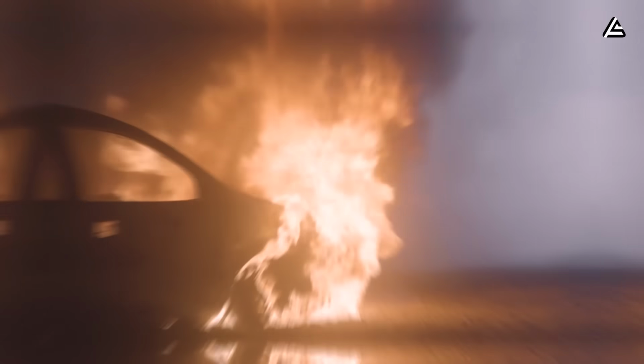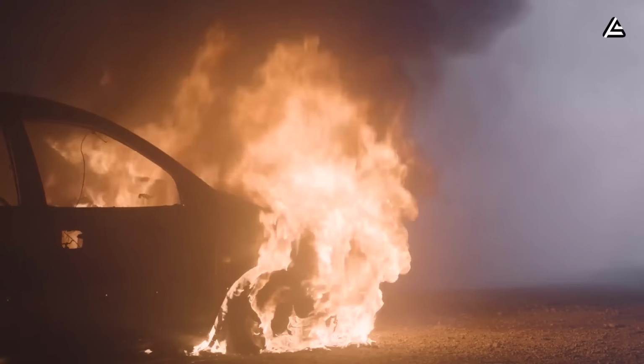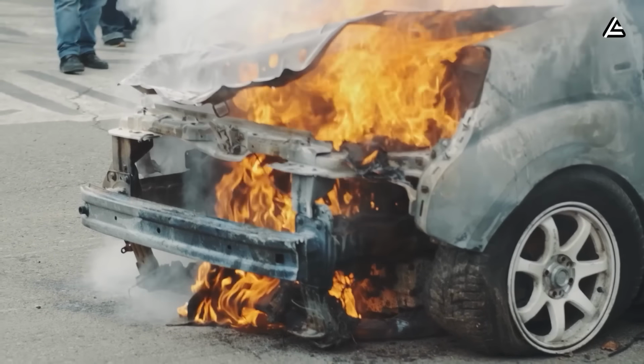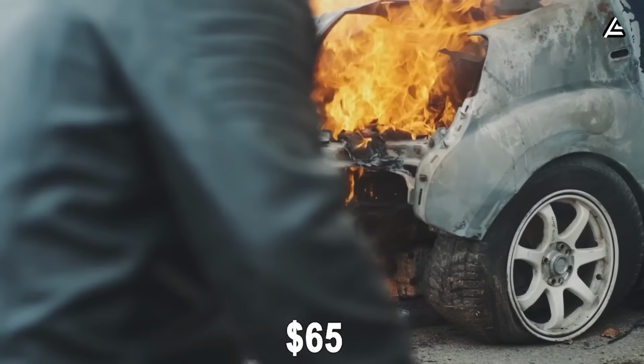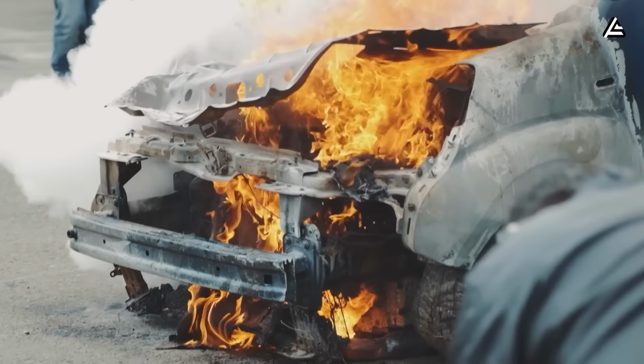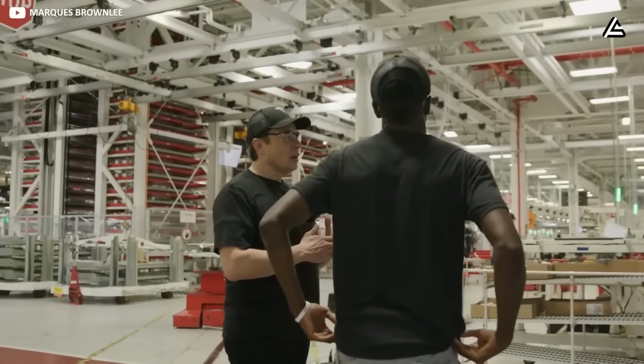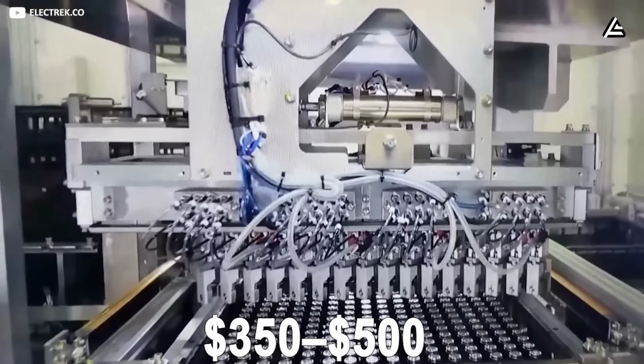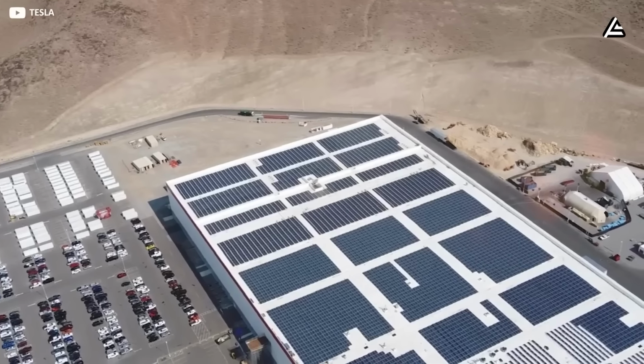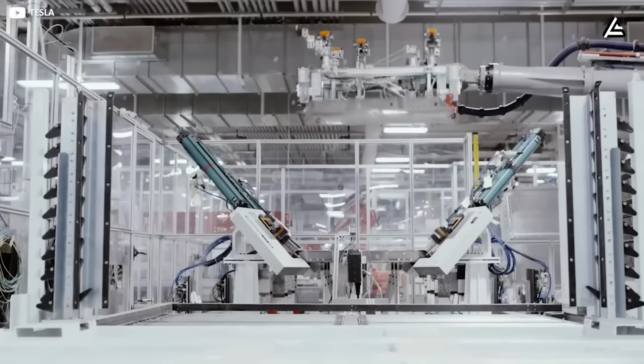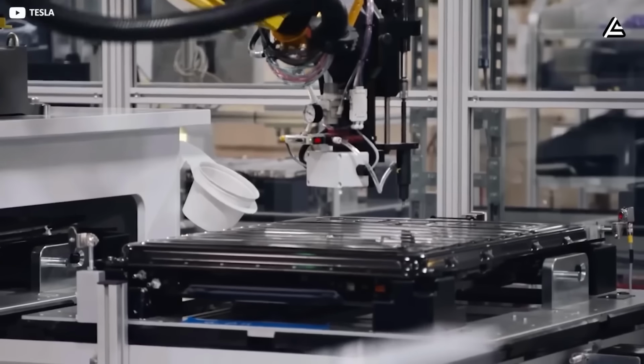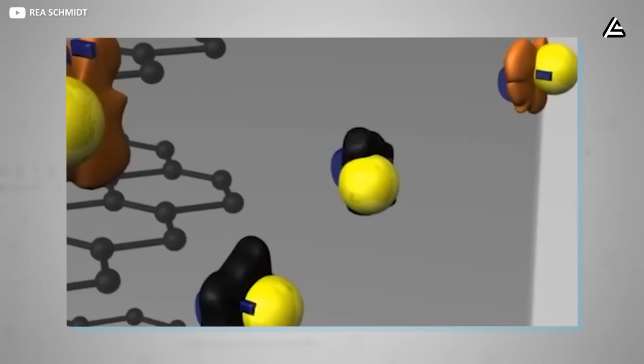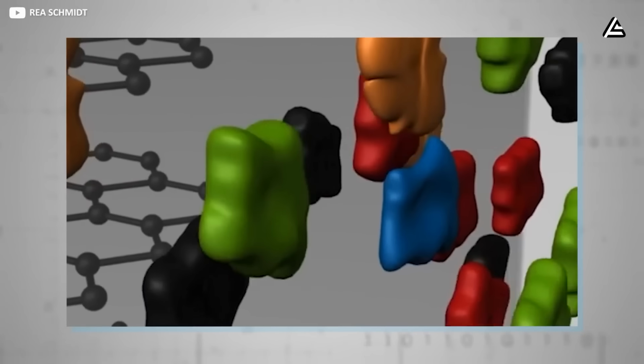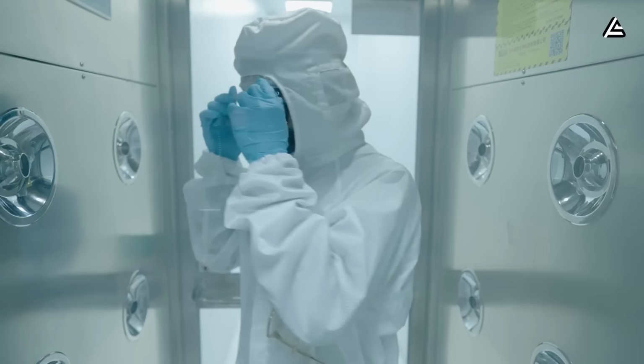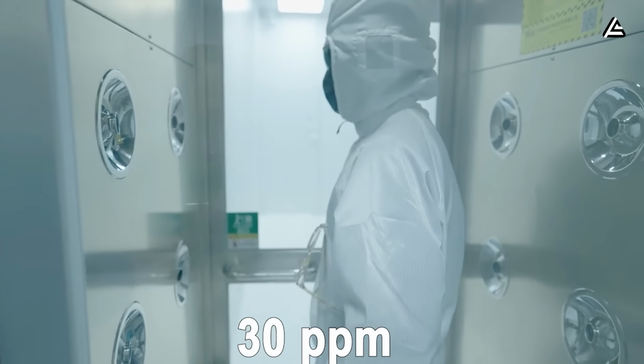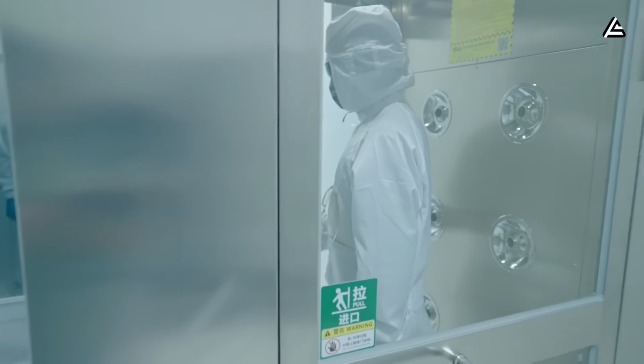U.S. fire departments now log an average of 1,800 lithium-ion EV fires every year, roughly 5 per day, with losses exceeding $65 million annually in damaged property and cleanup. Disposal is just as complex. Each retired EV pack costs $350 to $500 to neutralize and store, and a single warehouse holding 1,000 expired packs must spend $500,000 on fireproof containment alone. The electrolyte, lithium hexafluorophosphate, decomposes into hydrogen fluoride gas at 200 degrees Celsius, toxic at concentrations above 30 parts per million, forcing cleanup teams to wear full hazmat suits.